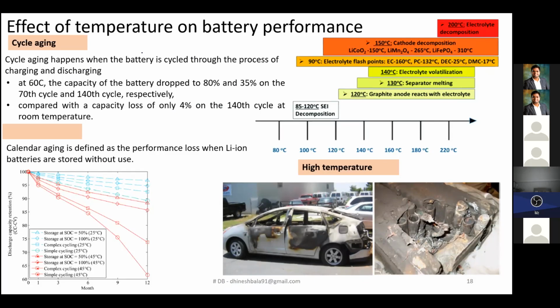So cyclic aging is where the battery is allowed to cycle based upon its charging and discharging cycle. Based upon recent literature, it has been stated that at 60 degrees Celsius, the capacity of the battery drops to 80% and 35% for its 70th and 140th cycle. So after 70 cycles, the battery state of health has dropped from 100 to 80% when you are operating your battery at the temperature limit of 60 degrees Celsius or above, because we are very much aware that the safety limit of a lithium-ion battery is 60 degrees Celsius. And when you operate at 60 degrees Celsius or even further, your battery state of health has stepped down from 100% to 35% for your 140th cycle, compared to the capacity loss of around 4% in the 140 cycles.